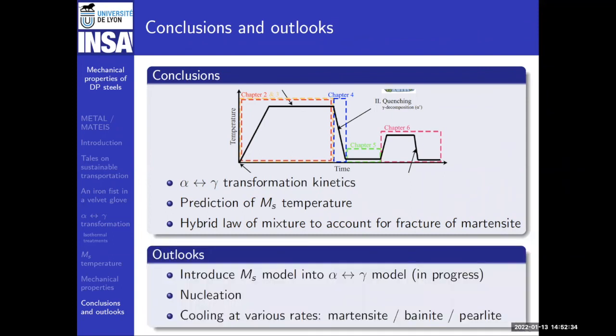So as far as outlooks are concerned, the idea would be to introduce the martensitic model, the quench model, into the transformation model to be able to model the movement of the interface back from the austenite, but this time to martensite. This is quite complicated because this is not a diffusive transformation now, it's displacive. So it's another physics. We have to introduce another physics in the model, which is not based on diffusion. Maybe we have to introduce nucleation of martensite in this model. And of course, the holy grail would be to model continuously martensite, bainite, pearlite, depending on the cooling rate, to have all the transformation rates that are possible. Okay?